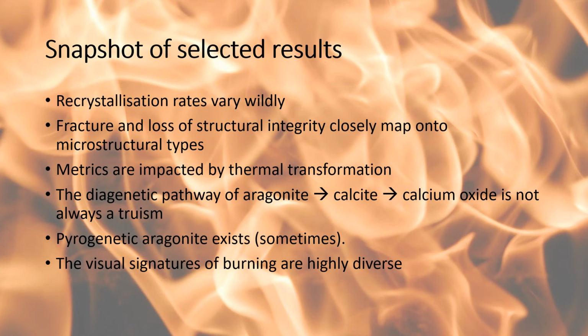Fracture, delamination and disintegration patterns closely mapped onto microstructural types and the placement of organics within these structures. Thus, prismatic structures came away in blocky sections because prismatic structures are built in blocky sections, while nacre delaminated prior to shearing. These are really exactly what you would expect. If you reduce the organics, you lose the glue. Metrics were noted to be impacted by burning, with shells sometimes reducing in overall size due to dehydration, and sometimes expanding in size due to delamination and the splitting apart of layers.